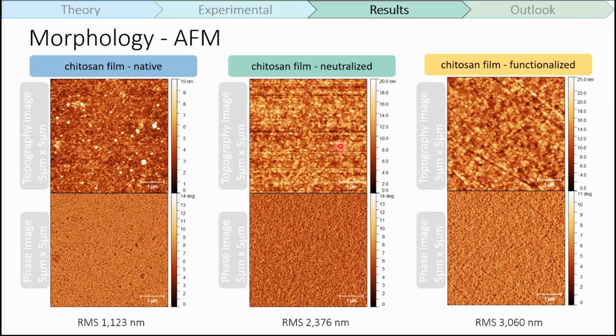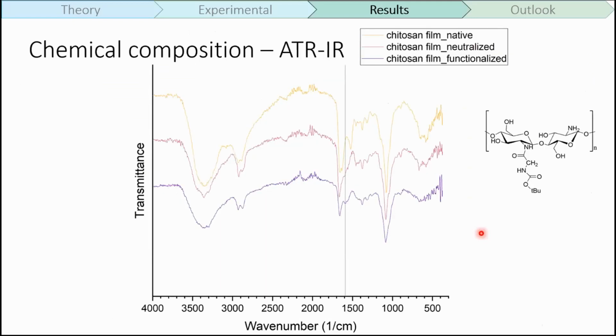With the morphology images, we once again see that the particle size gets even larger with functionalization. There are some surface changes that we can observe with AFM images, also confirmed by the increased roughness. From the phase images, you can still see that the film is pretty much intact, with no holes or other damage done to it. It's still quite uniform after functionalization.